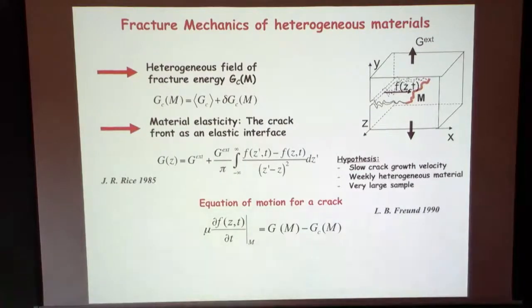The elastic energy, and so if you have something that's inertial, it is less likely to satisfy that condition too. It actually works well under slow loading, but when the crack is moving at the speeds of information in the material, because this equation of motion, a crack has, in theory, no inertia. It's like a massless particle. So this df/dt is just the instantaneous velocity of the crack at every point z at every t.